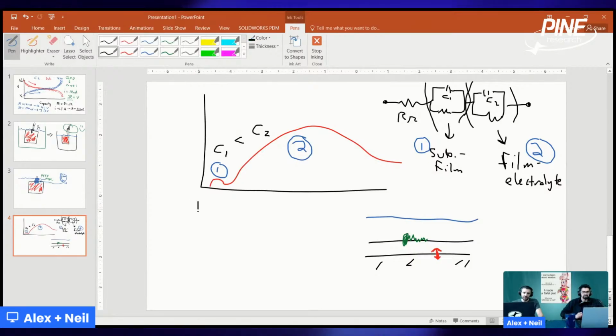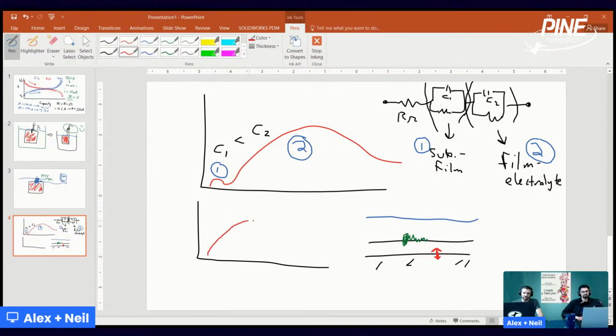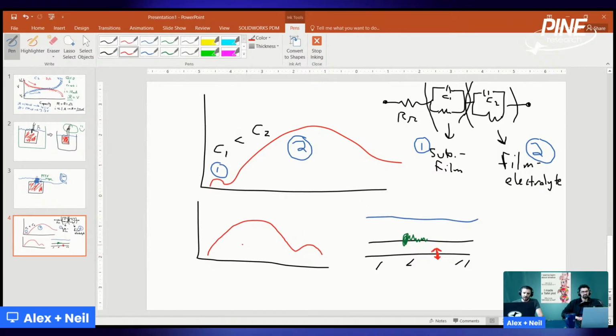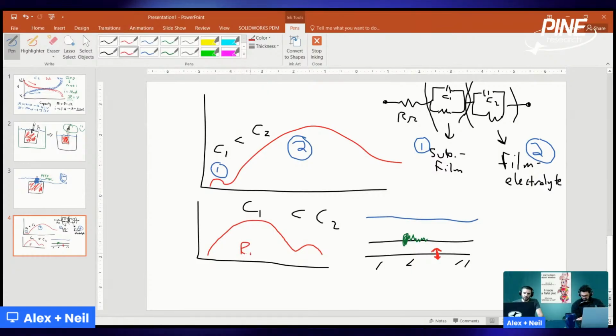Now, what you said is you have a big arc then a small arc. What I just described can still be the case. It just means that the resistance of the first one is bigger. So if you have something like this, you still have C1 less than C2, but R1 is greater than R2 for whatever reason. This could be poor adhesion. There's not much capacitance here, but there's a lot of resistance. Maybe the film isn't sticking well to the substrate, so there's a high resistance or high impedance there.